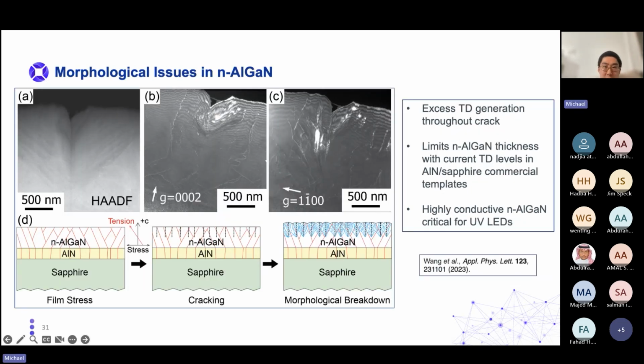These are just different cross-section views of this crack in transmission electron microscopy. And here's a basic schematic. So what happens is when you start doping this aluminum gallium nitride with silicon, the threading dislocations that were vertical start inclining and adding misfit components. The stress goes from compression to tension, and eventually the material just cracks and then generates a lot of threading dislocations. And this also explains the volcano formations on very thick material.